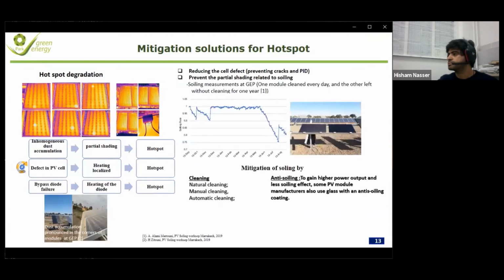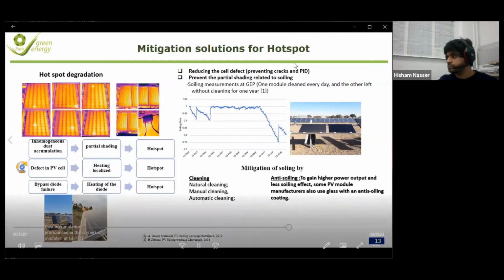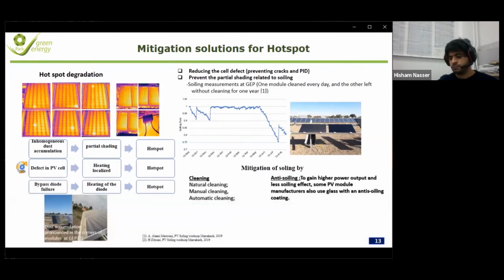For the first one, it's necessary to reduce cell defects by preventing cracks and PID. So we talked about cracks. Also, it's necessary to prevent partial shading in the PV module, which is very pronounced in the climatic conditions of Morocco, and especially in Ben Guerir, by cleaning or by using anti-soiling, and also using a coating to improve durability and to gain high power output against the soiling effect.